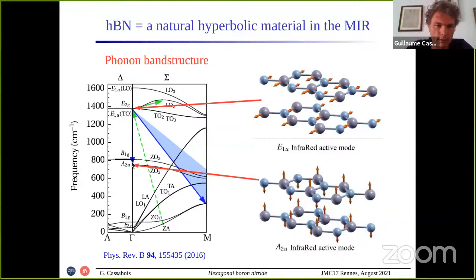If we now switch to this other transverse optical mode, called the ZO mode, the atoms vibrate along the C-axis, which means light will be absorbed for an electric field in the plane in this case. So we will have properties for an electric field in the plane for this Reststrahlen band, whereas in this case we will have light absorption by the optical phonons for an electric field parallel to the C-axis.